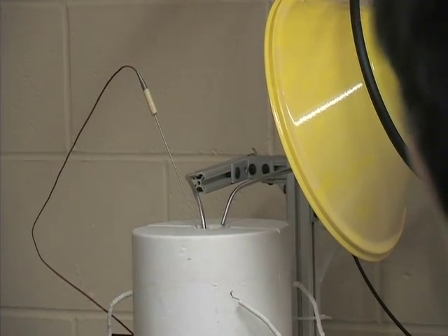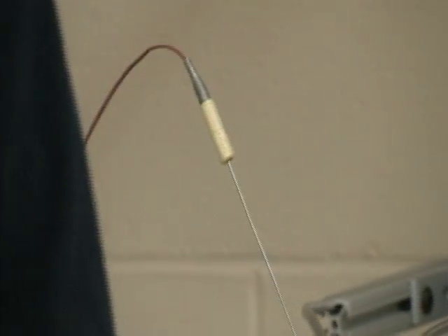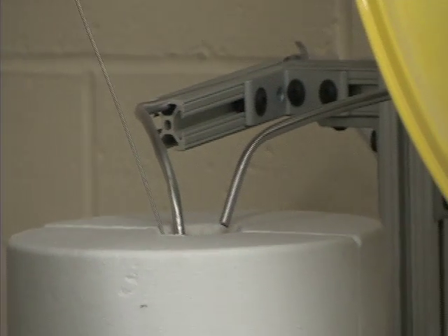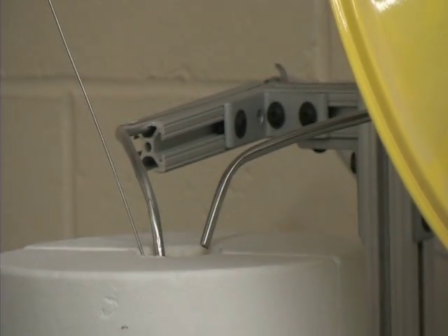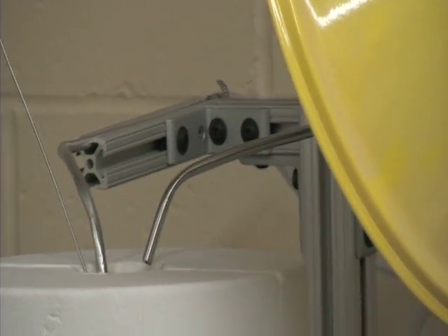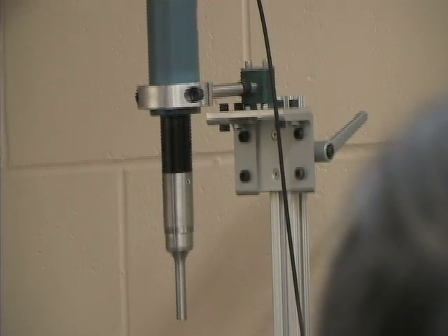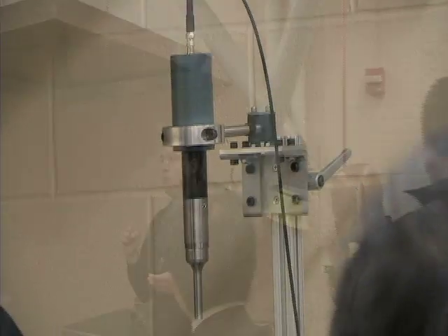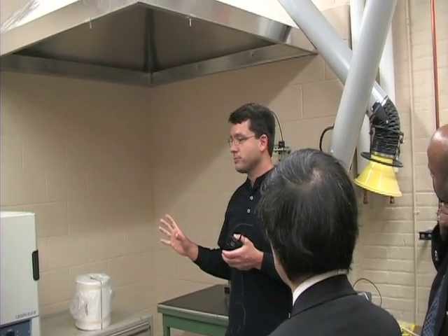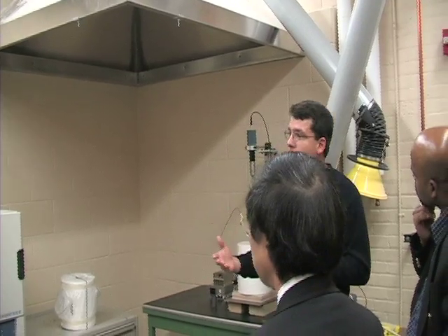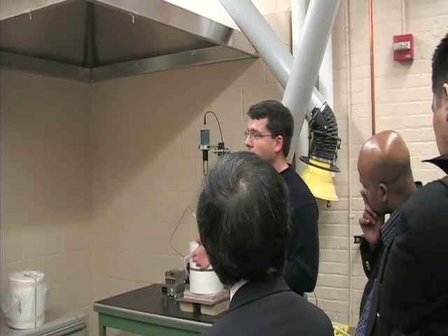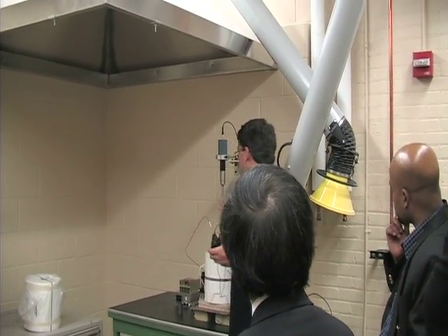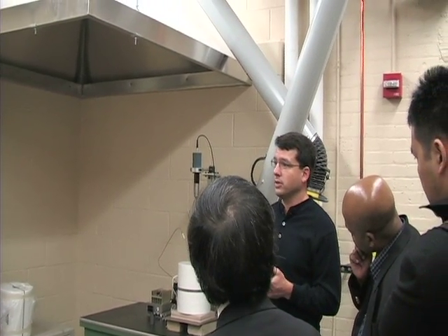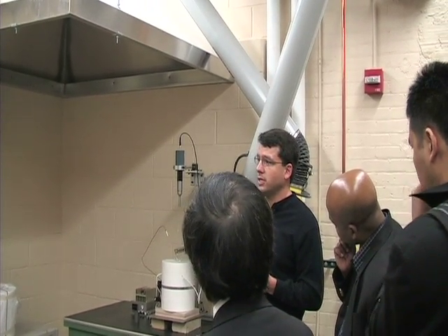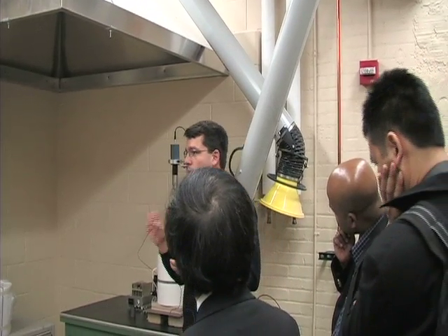When you make these materials, the real trick is getting the nanoparticles broken up and well dispersed into your material. Due to the high surface to volume ratio of the particles and the high associated interfacial energy that you create as you disperse the particles, the nanoparticles really like to agglomerate and they really don't want to break up and disperse into your material. To overcome these problems inherent with nanocomposites, we use an ultrasonic technique to break up the clusters. The ultrasonic energy creates cavitation events in the melt. These break up the clusters.